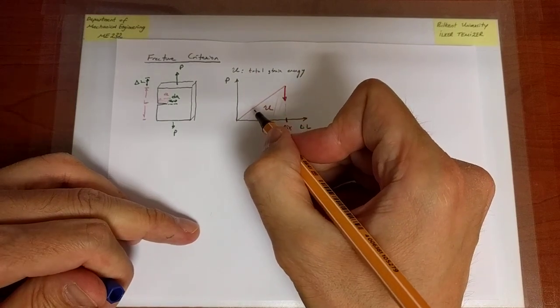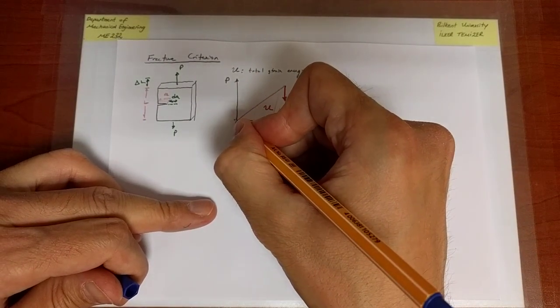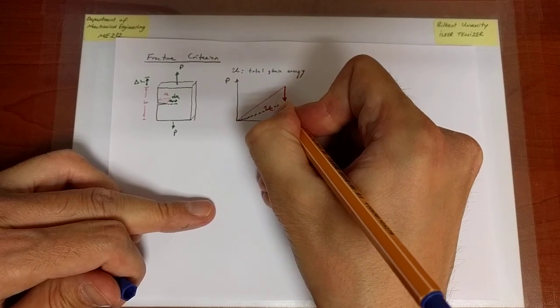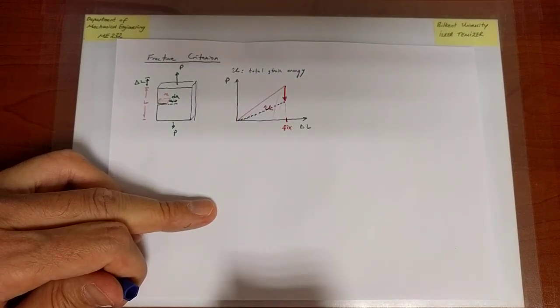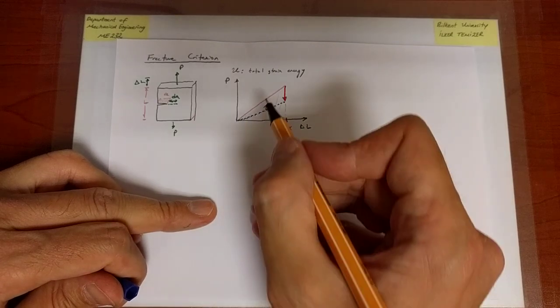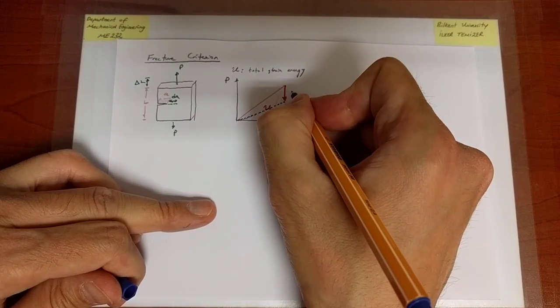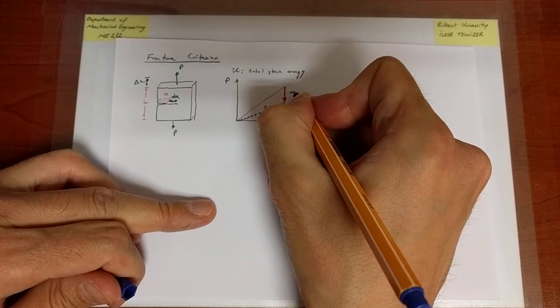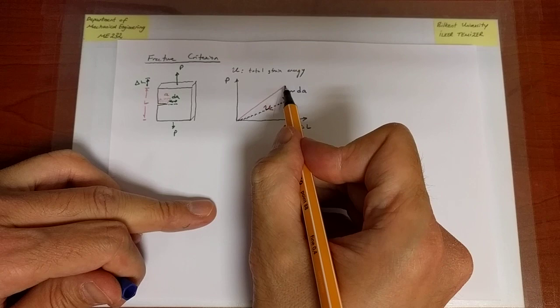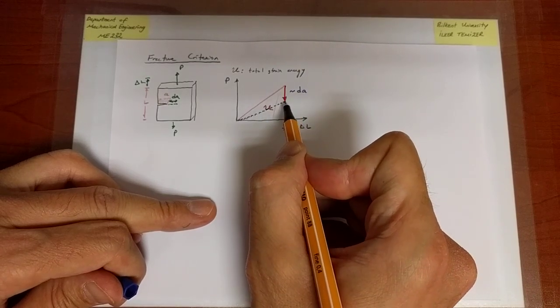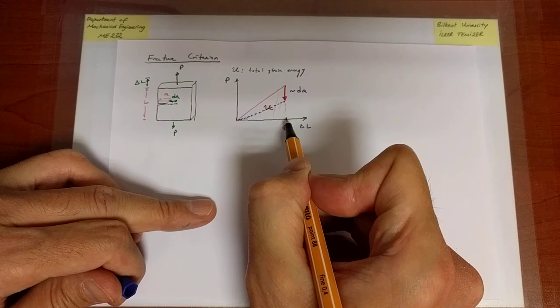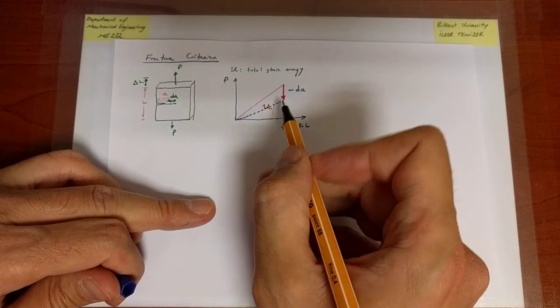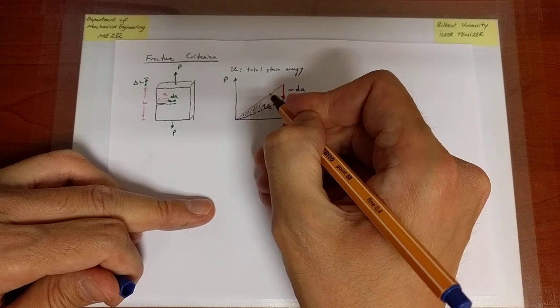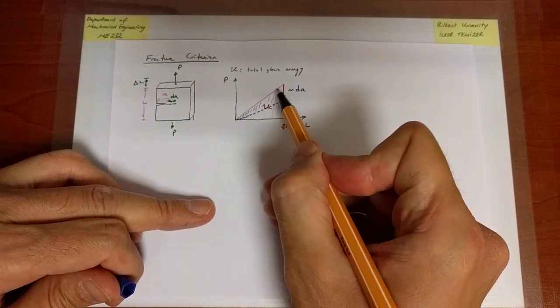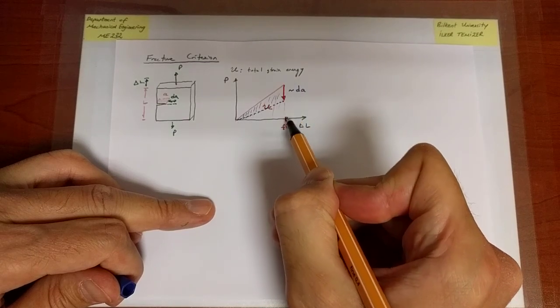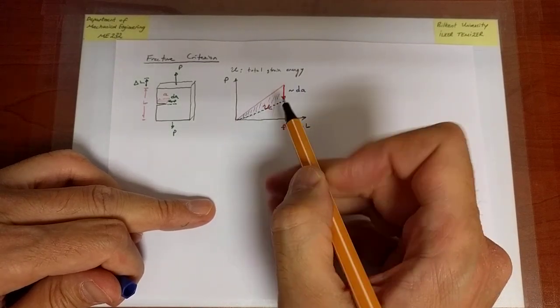Now, when the force gets reduced as a result of the virtual propagation of the crack, the net amount of energy that has been stored in the system will also get reduced. Originally there was U, and now suppose there was a change in the crack size, an increase in crack size, which caused a decrease in the force, and because the tip of the plate is being fixed, the amount of elongation, what happens is that the total amount of energy that is stored in the system has been reduced from this amount to this amount. And the difference is the amount that I have shaded.